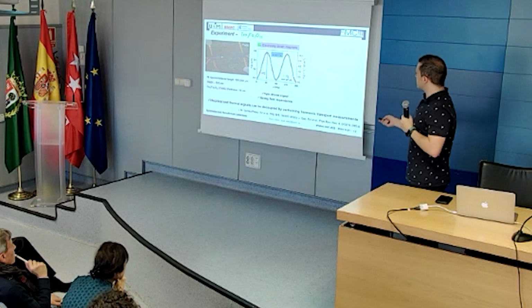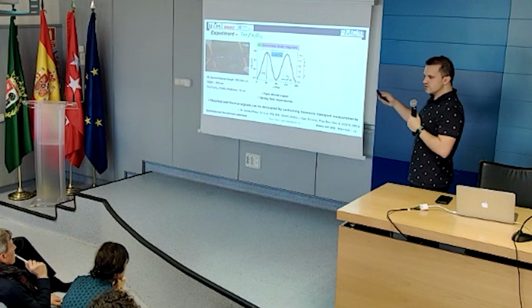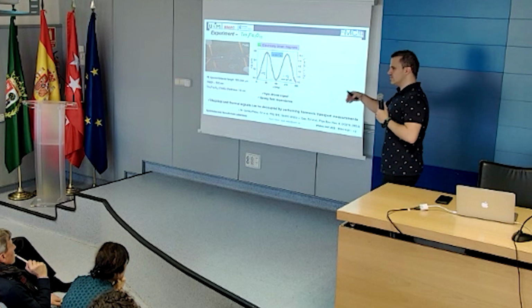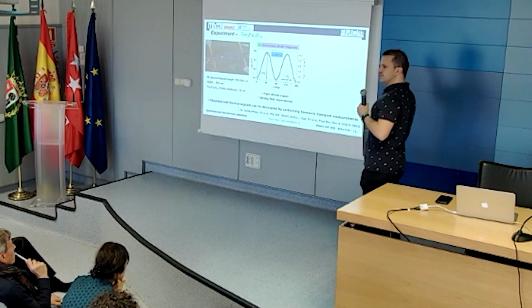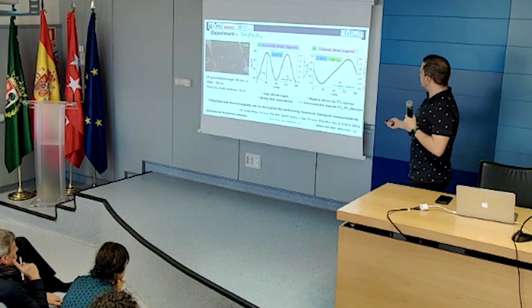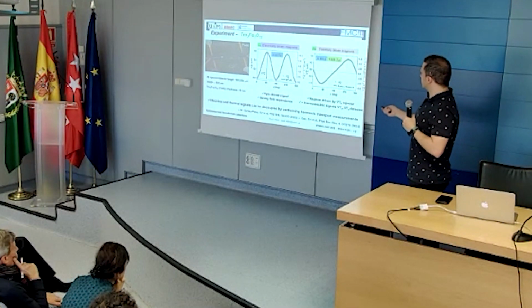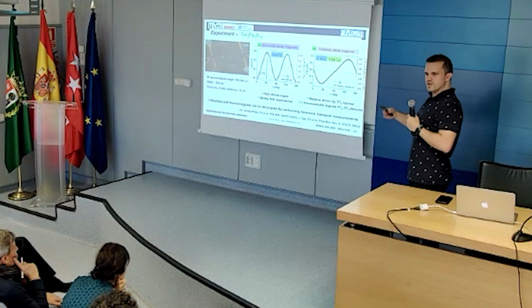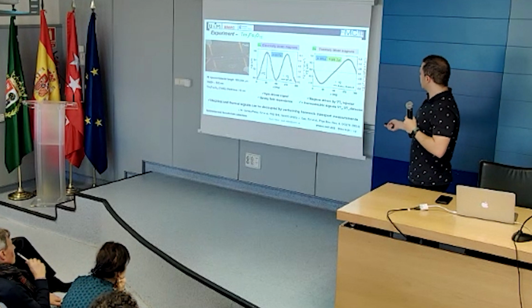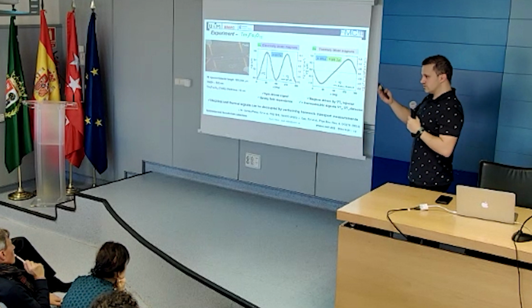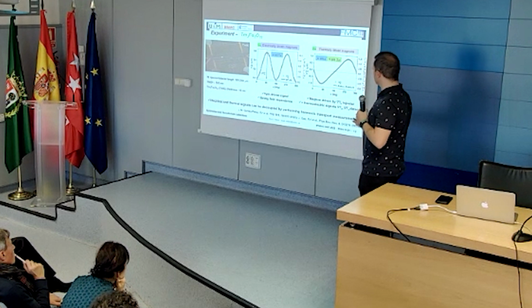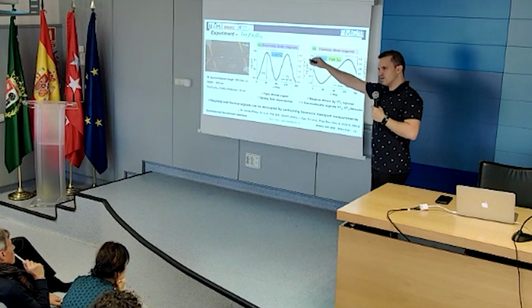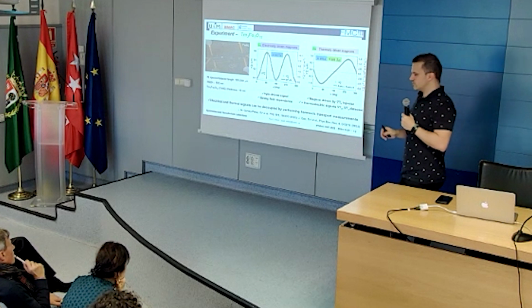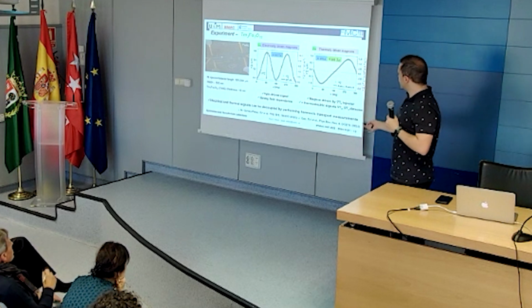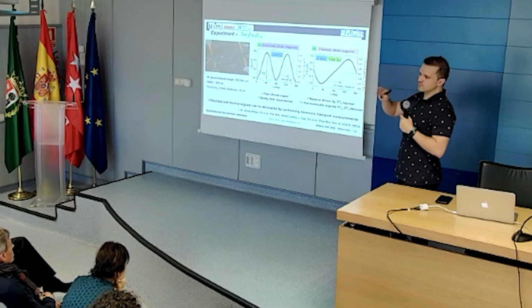And that's how a measurement looks like for the spin-driven one. It looks like a sine squared, and that's just because of the symmetry of the spin injection at the injector and the spin detection at the detector. And in the case of the thermally driven ones, we have a little bit more than just picking up magnons, because you can also have thermoelectric effects. So you have magnons that are driven by the out-of-plane thermal gradient at the injector, but you can also have thermoelectric effects, because in the end you will also have thermal gradients at your detector, and you need to also account for this.